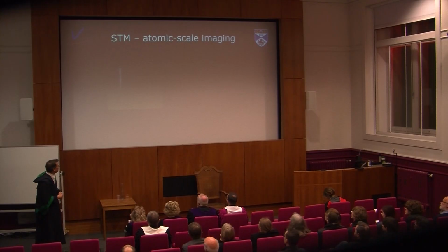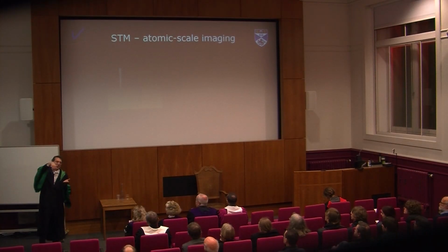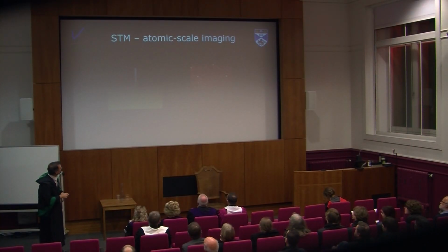That gives you a bit of an idea of the challenge we face when we try to stabilize these tips in front of the surface. If it works, oh, this is a bit dark, but here's the tip, this is the metal surface. If it works, we can basically raster scan this tip across the surface, and then we can record the current, and then we get an image of the surface.